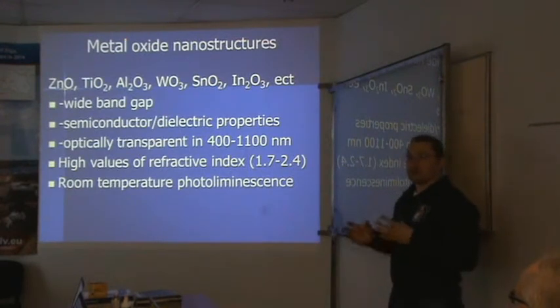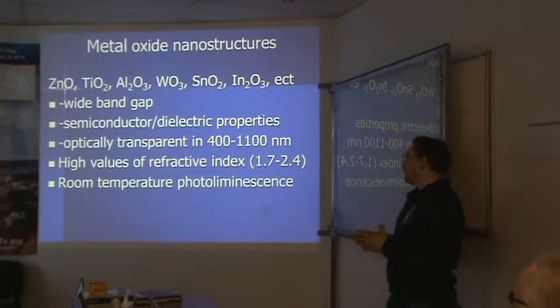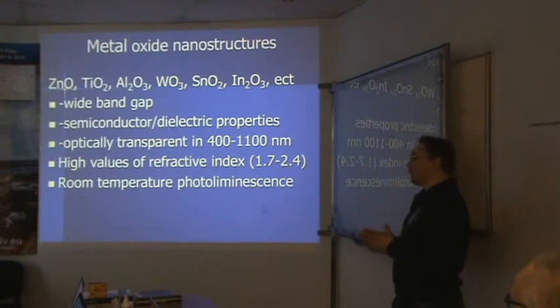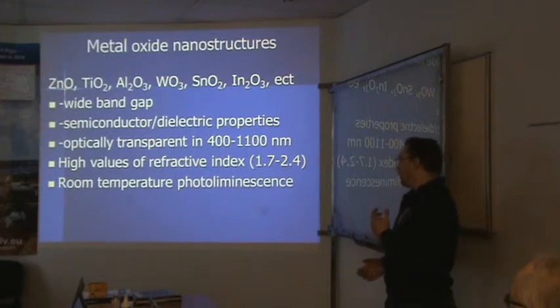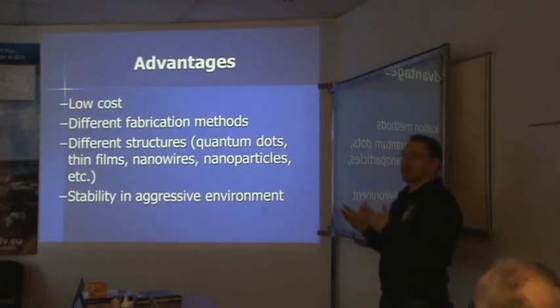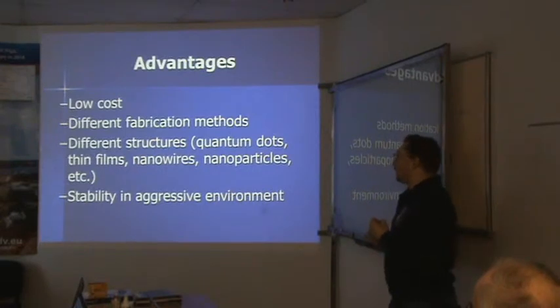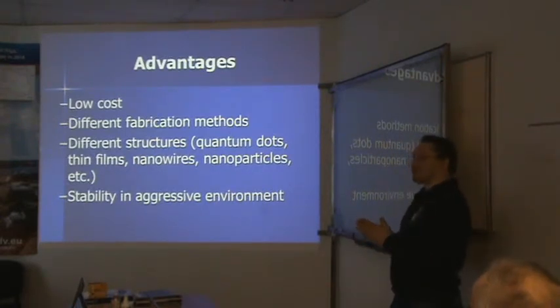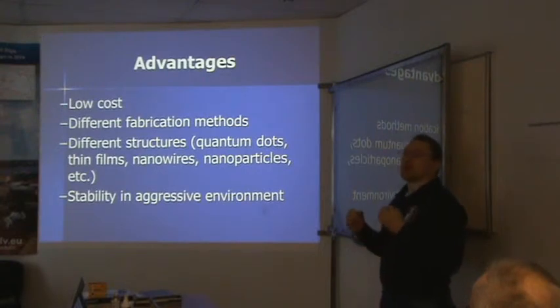Mostly our work was focused on metal oxide nanostructures because of their properties. These materials can be applied in sensors, biosensors, solar cells and optical coatings, because they have a wide band gap, so they are optically transparent in the visible range. They also have good optical properties like room temperature photoluminescence when you decrease the grain size of the particles to nanoscale. Also, these materials have advantages for industrial applications, such as low cost, and there are a lot of methods for deposition, and you can tailor the geometrical parameters of these nanostructures.